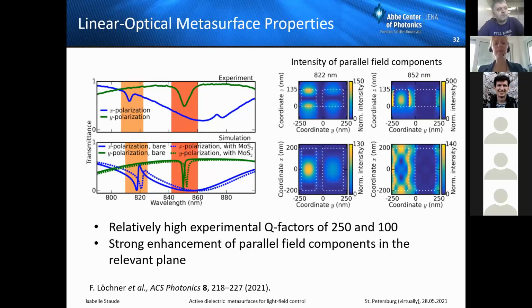So in principle, this nonlinear susceptibility of the TMD shows several peaks. It's strongly wavelength dependent, as you say, and the exciton frequencies are certainly where Chi2 will be enhanced, but we are also working in a sweet spot, namely this so-called C peak, which is the band nesting region of the TMD, where the Chi2 is also enhanced. The reason we're working there is our excitation laser, which is a little bit tunable, so we can make this kind of second harmonic spectroscopy, but we can't tune it to the exciton wavelengths. But as I said, it's also a region where the monolayer shows a strong second harmonic, which you always see at the C peak, giving strong enhancement.